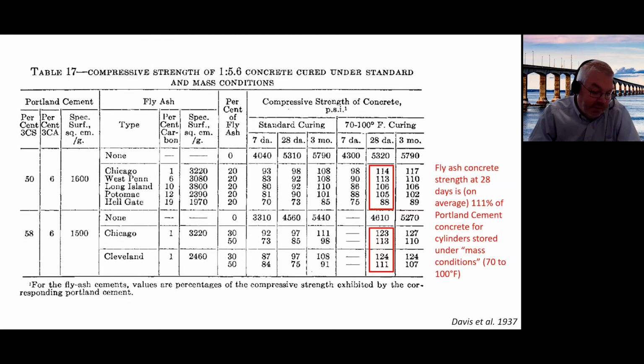And some of us have utilized this in our careers. We've used temperature match curing when we use fly ash to demonstrate that the early strength of fly ash is not as low as we would expect from regular standard curing.